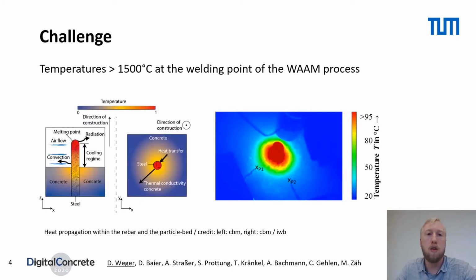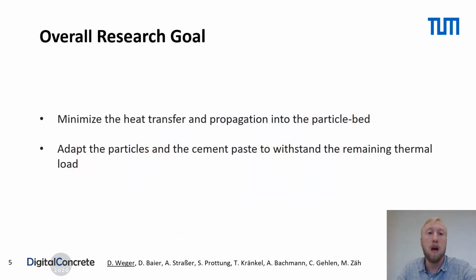The main challenge of the combination of these two methods are the high temperatures with more than 1500 degrees Celsius at the welding spot. Therefore, this feasibility study was done to check if it is even possible to use these two methods simultaneously. The overall goals of the research project are to minimize the heat transfer and propagation into the particle bed and to adapt the particles of the cement paste to withstand the remaining thermal load.